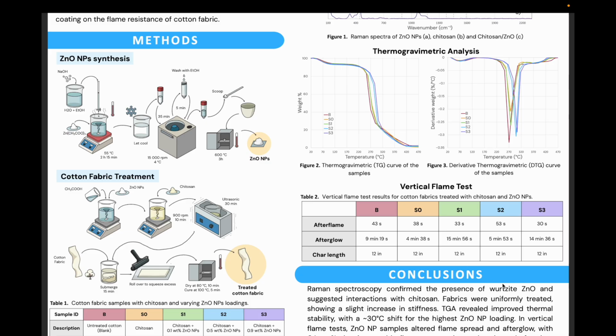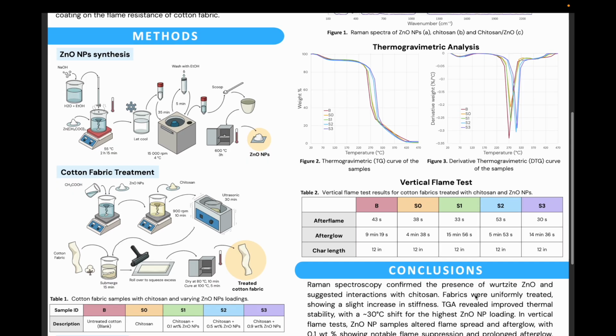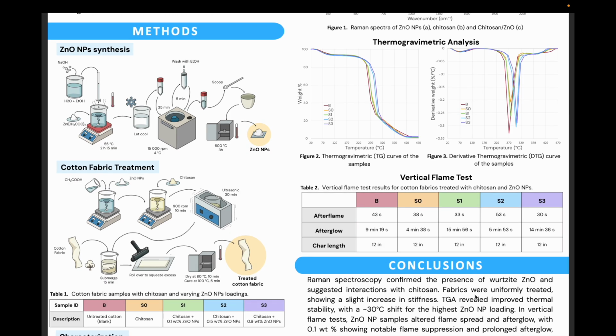Higher loadings also modify the burning behavior, but with different after flame and afterglow characteristics. For example, sample 2 performs similarly to sample 0, which is only chitosan, and sample 3 performs similarly to sample 1. So these results confirm that zinc oxide does influence the combustion pathway of cotton, even at very low concentrations.